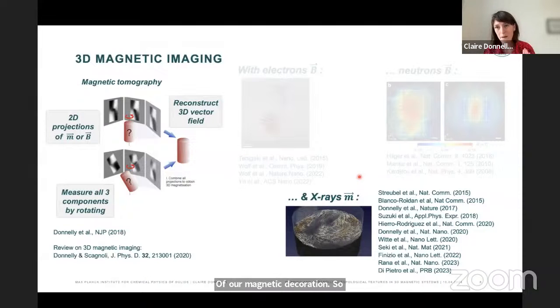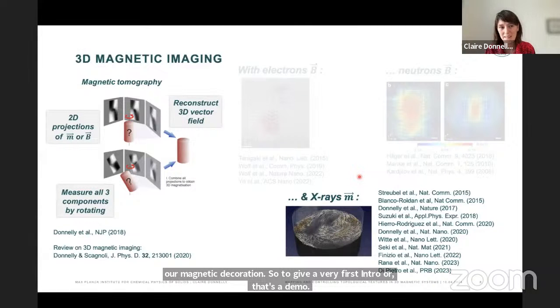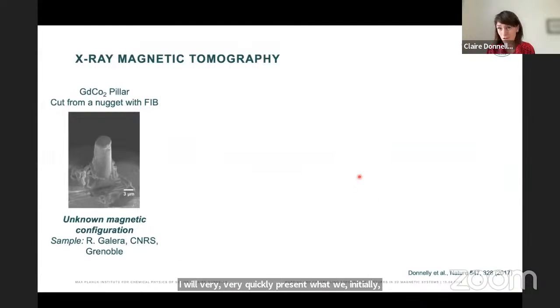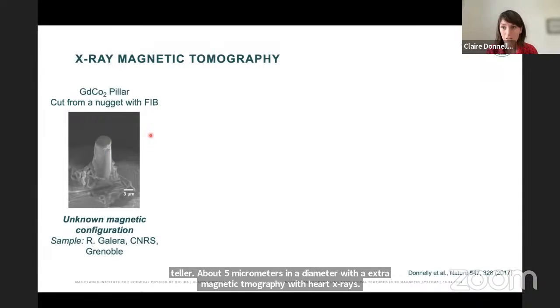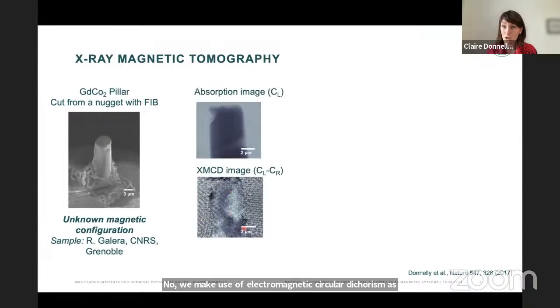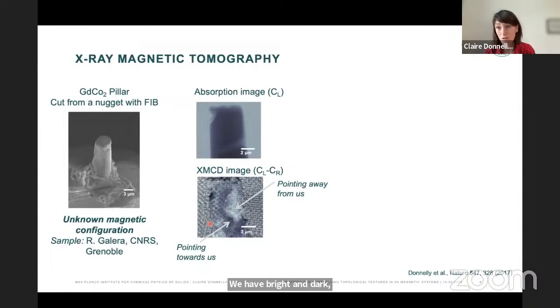So to give a very first intro, or let's say demo, I will very quickly present what we initially published as the first demonstration of magnetic tomography quite a few years ago by now. This is where we looked at a ferromagnetic pillar about 5 micrometers in diameter with X-ray magnetic tomography with hard X-rays. We make use of X-ray magnetic circular dichroism as our contrast mechanism. You can already see in these two-dimensional projections that in the lower half, where we take the difference between circular left and circular right, we have bright and dark regions, which correspond basically to the magnetization pointing towards or away from the screen. We typically measure as part of one of these data sets about 1,000 of these projections, or in this case, we measured about 1,000 of these projections around 2 different tomographic rotation axes.